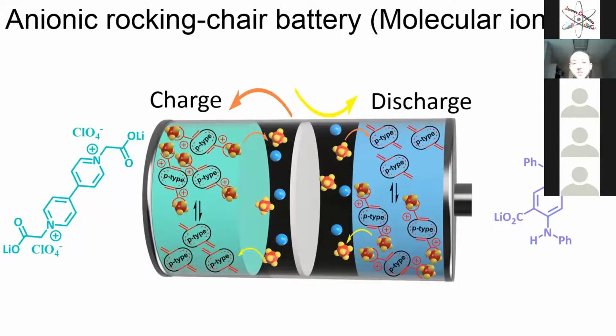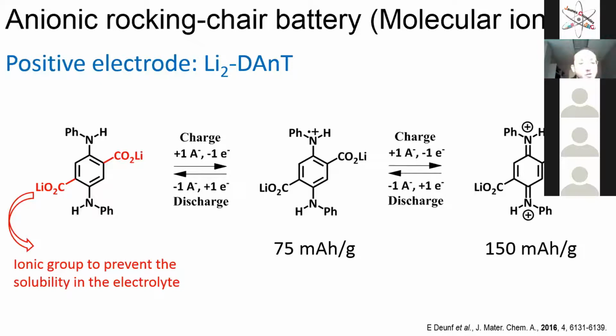So the example that I talked about is this one. We are using viologen derivatives with a conjugated amine as a positive electrode. For the conjugated amine, here we introduce, as you can see in red, a carboxylate, which is the ionic group. We use this to prevent solubility, because here we have a small molecule, and if you don't use this ionic group, it will dissolve. So if you want to prevent the solubility in the electrolyte, you add these ionic groups. And by doing this, you will have a stable molecule in the electrolyte, and you can charge it.